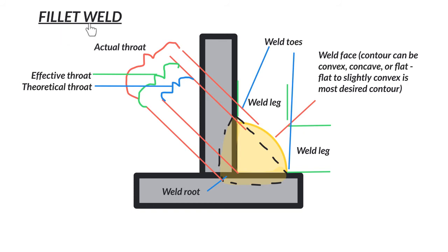Next is a fillet weld. We talked about the triangle — let's start at the top with weld toes: toe one and toe two. Toes should tie in. That's usually where we find undercut — we don't want undercut. We also don't want cold lapping, where it looks like the bead just sits on the actual metal. That can happen with colder processes like short-circuit MIG welding when going too slow — the settings are too slow, it's not really tying in, it's just building up at the toe.